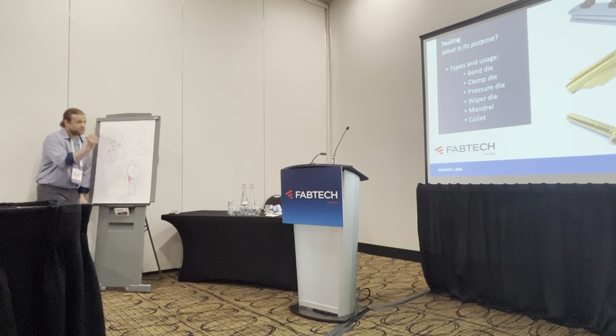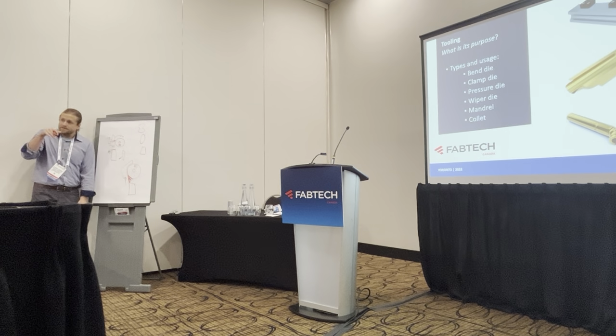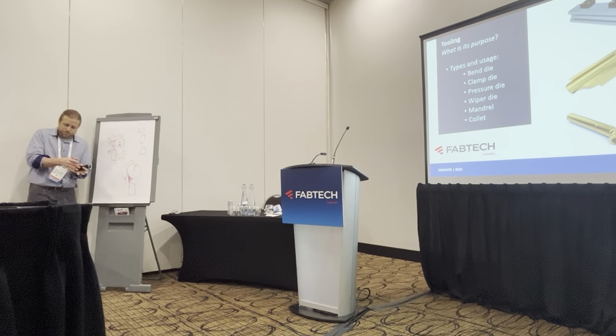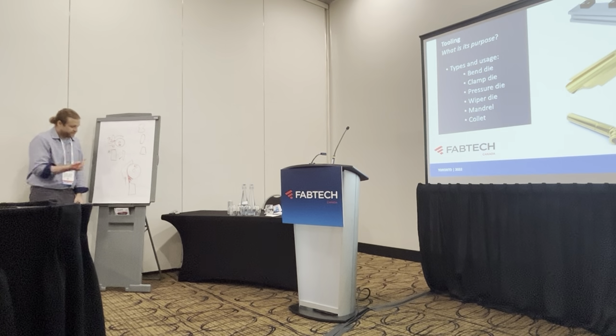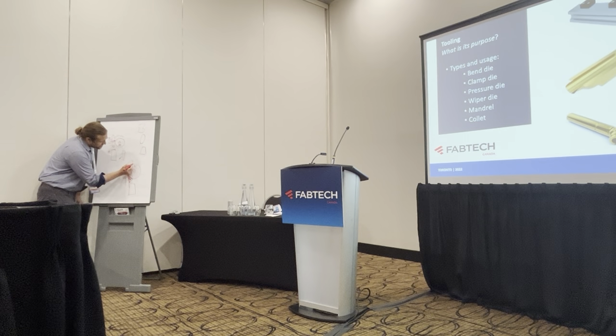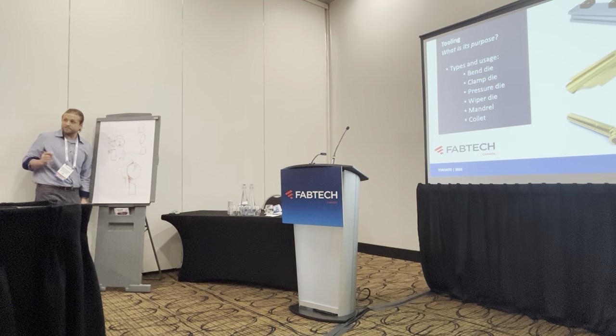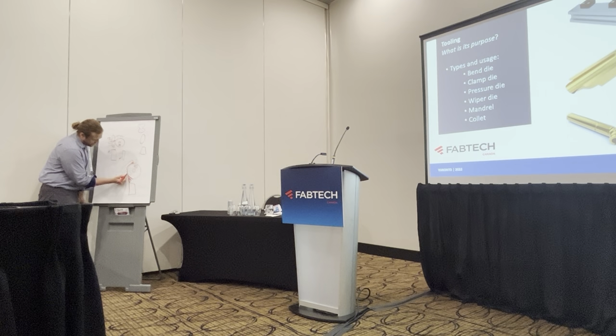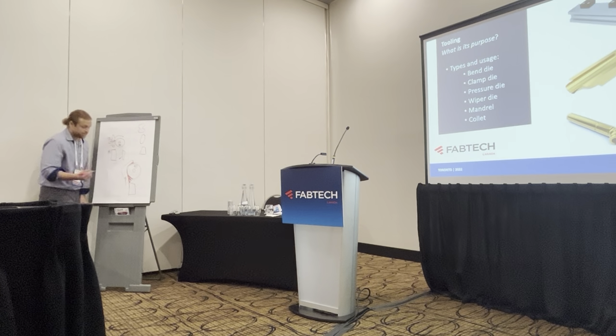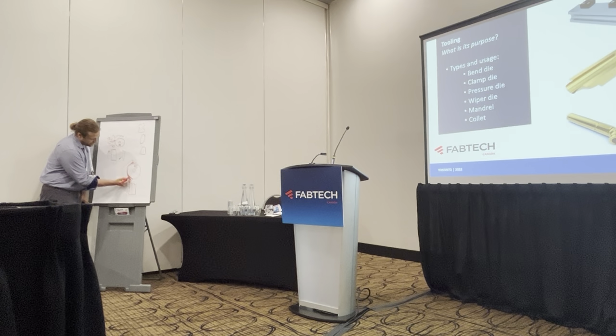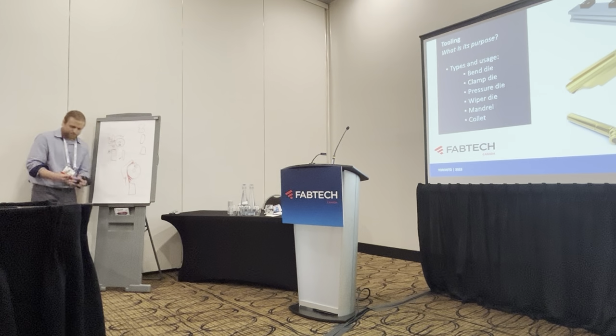The problem is as you get closer to 1D, the difficulty of the bend increases, and the resistance on the front end is telling the material, stop forming this direction. I need you to find least resistance. So what the material likes to do is it says, okay, I got a nice gap right back here. I'll just start filling this gap in. So that's how your wrinkles occur. The material ends up filling this gap in and then pushes it through, and the wrinkles form out and you end up with a bunch of wrinkles in the back end.